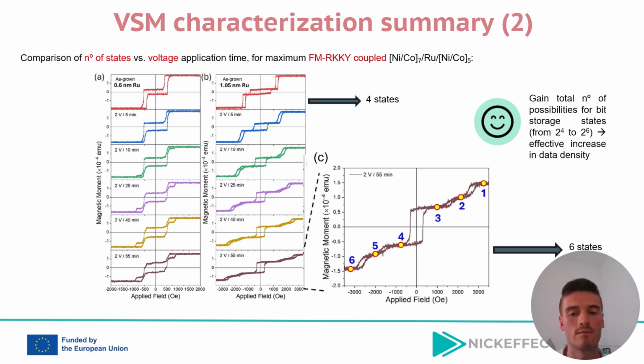If we compare the as-synthesized state and the 2 volt, 55 minute gated state, this is illustrated in charts A and B, particularly B, and C, for this 55-minute gating case study. In practical terms, this is of great interest to gain in bit storage areal density, which could be tremendously useful for...